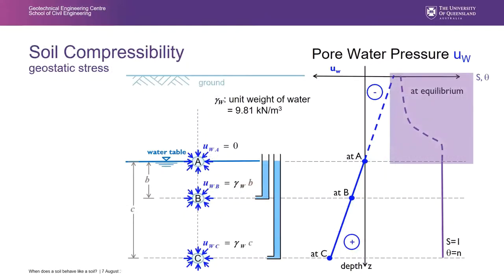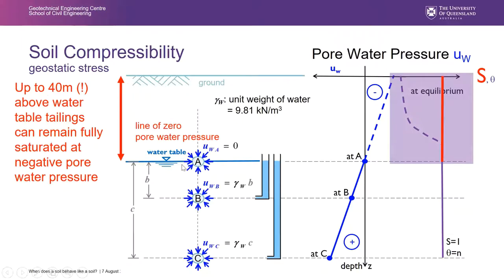So what that means, if we would, for example, have this kind of condition in the tailings, in this case we should not define the water table as a visible line between water and air. It is rather what we call the zero potential line, or the line of zero pore water pressure. So if you would measure with a pressure transducer at that location, zero pore water pressure, that would be that line. But above, up to 40 meter, the soil stays fully saturated because of this behavior, unless we have any evaporation on the surface. But this is important information when you think about any water balance processes in tailings.